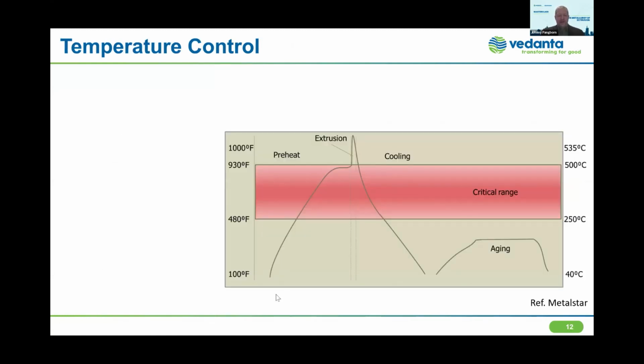What does this actually look like at extrusion? Well, here we have a schematic that's showing our process as we heat up through extrusion. Of course, we're starting at ambient temperature. We are coming up through temperature, we're extruding, and then we're cooling down. So we'll focus on that. We have Celsius and Fahrenheit on this, but in this range, from about 250 to about 500 Celsius, this is what we call a critical range, and this is really important. First of all, because we have to deal with this. We cannot avoid this or pretend it doesn't exist, because our process is proceeding first up through and then down again through this critical range.